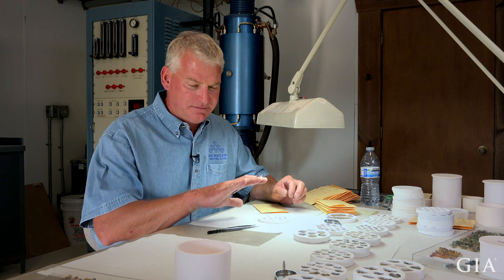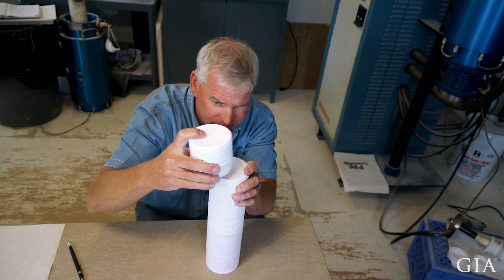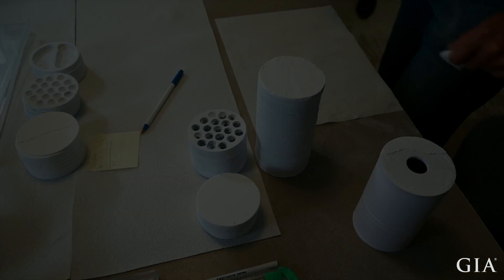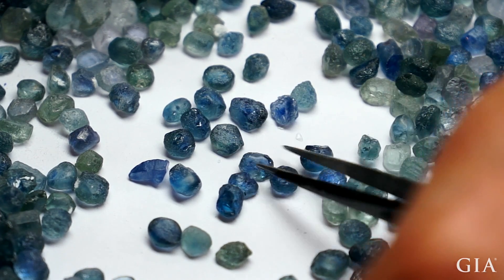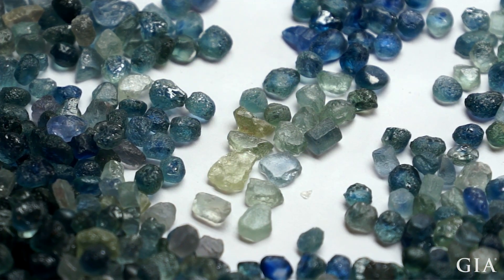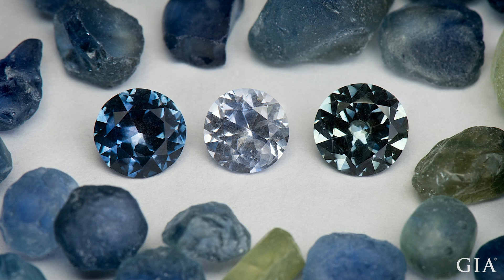A good 40 to 45% of these now-green sapphires will be a very nice blue after the blue burn. Around 45% of the stones are going to come out a spectacular blue color. There's always a lot of discussion about whether to heat treat or not, but in the case of our material here at Gem Mountain, there's just no question at all that the heat treating adds a tremendous amount of value.